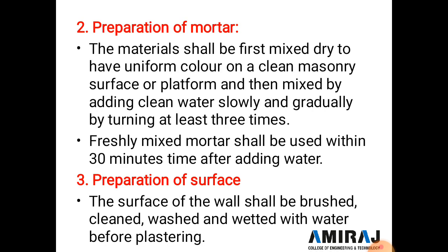The second detailed specification for plasterwork is the preparation of mortar. The materials shall first be mixed dry to have a uniform color, on a clean masonry surface or platform, and then mixed by adding clean water slowly and gradually, turning at least 3 times. The freshly mixed mortar shall be used within 30 minutes after adding the water.